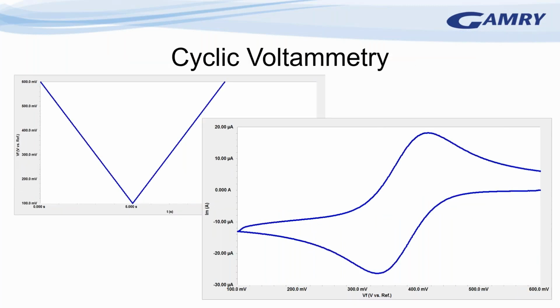In the case of cyclic voltammetry, on the right we show the ramp where we're changing the potential of the electrode at a constant rate to a particular limit, and then reversing that, and the resulting current gives you this classic what's called a duck shape cyclic voltammogram for a reversible electrochemical couple.